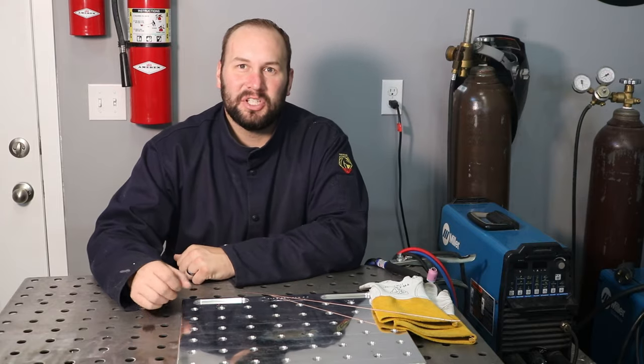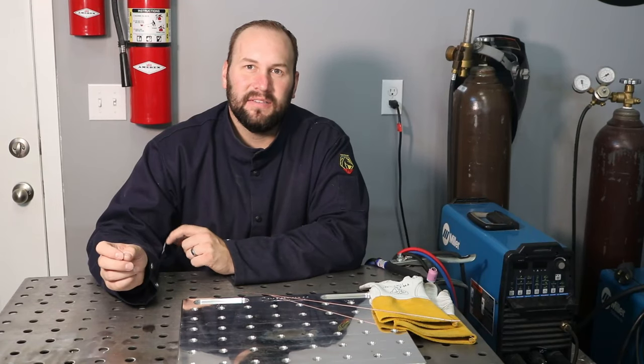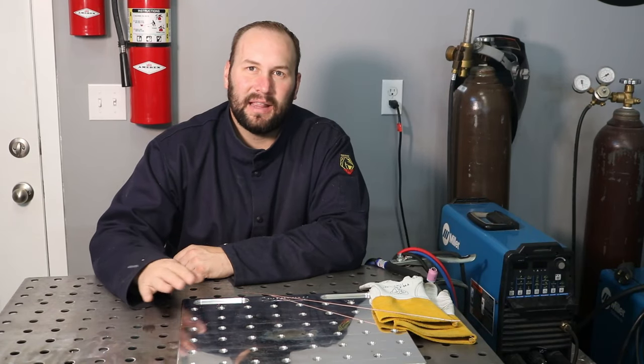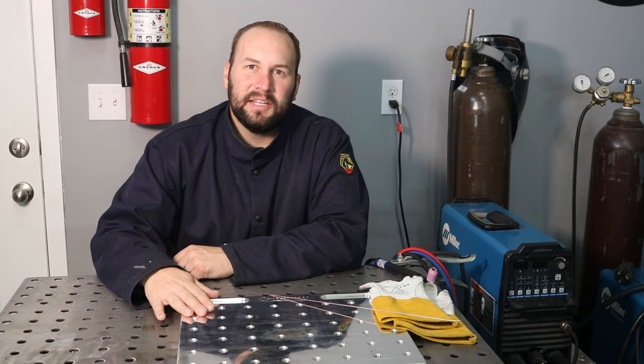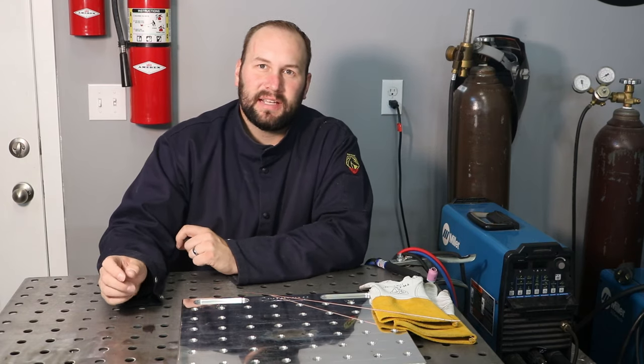I'll set my machine to alternating current in order to weld aluminum, because aluminum has a stable oxide layer, and by switching between your torch negative, like it is when you're welding steel, to positive, and having that switch back and forth, it'll actually clean the metal. You can see as I strike an arc here, there's kind of a fuzzy zone around the arc, and that's where the material is being etched and cleaned off, that oxide layer is being removed. And then you'll get a nice pool going there.